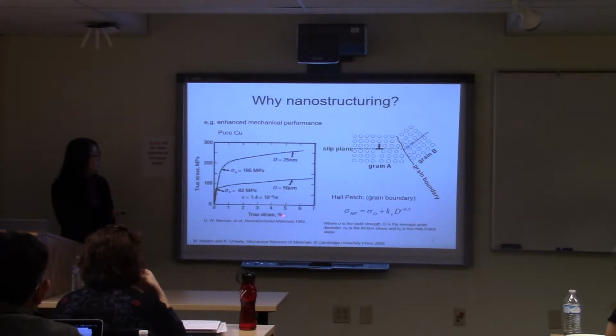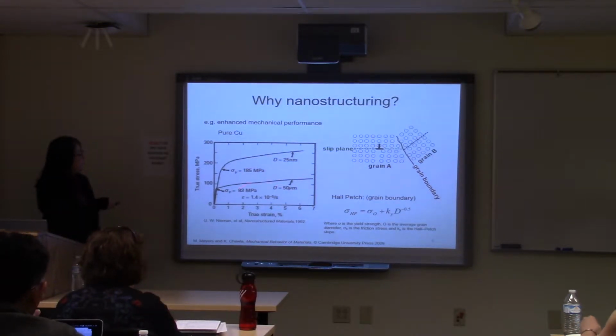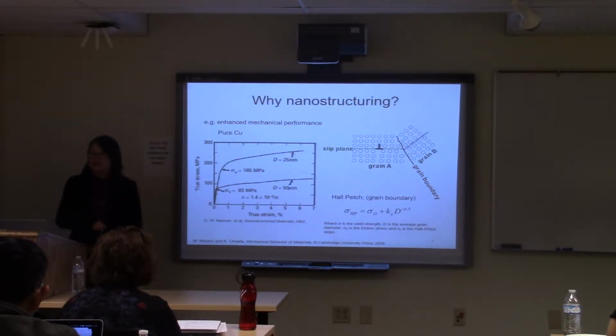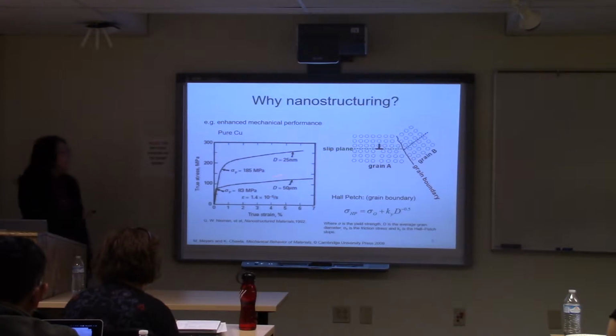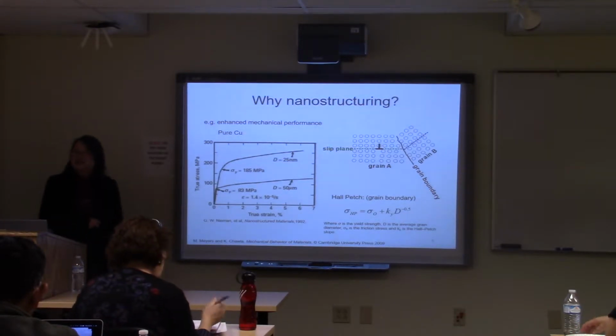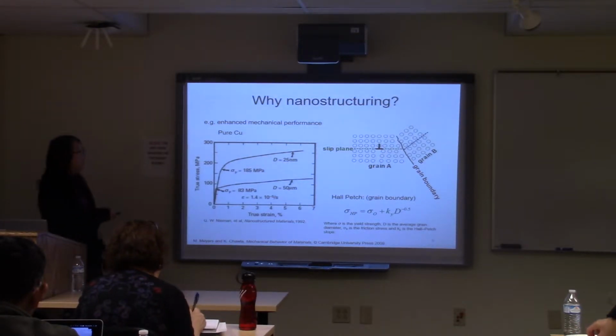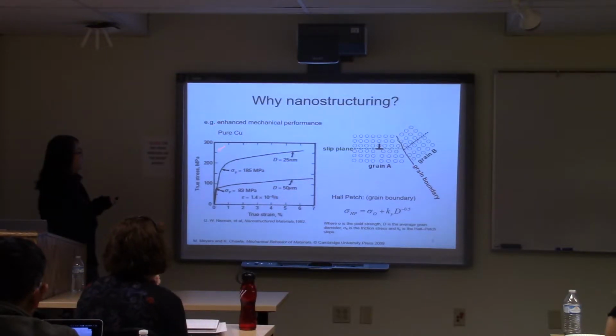True stress and strain curves. The lower curve is for traditional material, which has a grain size of about 50 microns. But once you reduce the grain size to 25 nanometers, you get a dramatic increase in strength. So you see the benefits we can get from nanostructuring.